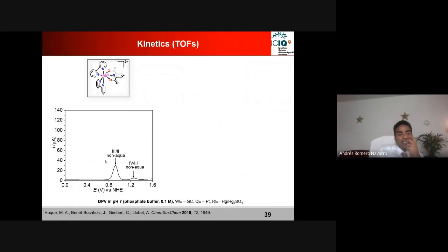So here I'm showing this DPV. That is the complementary experiment to the cyclic voltammetry. So here also you are measuring the current by changing the potential. So we had this molecule, and what we found is that if we apply the potential here for a while, and then you do this DPV again, you can see a huge increase of this anodic current, and that current is responsible for doing this water oxidation.